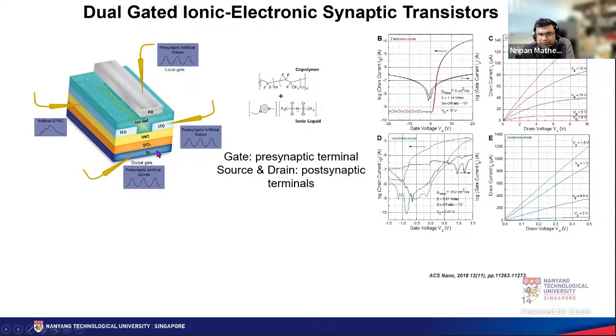Once you apply a positive voltage over here, electrons accumulate on this indium tin oxide and the transistor turns on. Over here, you can see that the resistance is high at negative gate voltages, and above a threshold voltage, the transistor turns on and there is a lot of current through it. It's a TFT, so it works in accumulation mode, unlike a MOSFET, which works in inversion mode.